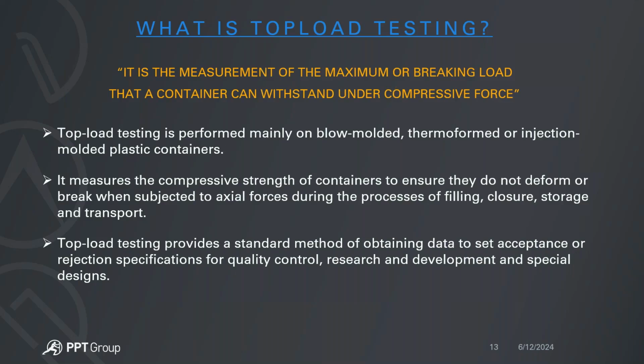One of the things that happens in any testing environment is once you've preset your pass or fail criteria for all future testing, you're then able to determine your pass or fail by saying, on this 20-ounce or 40-ounce bottle, we expect a minimum of 200 pounds. Anything above that is a pass. Anything below that is a fail. And that establishes testing standards for your testing environment in order to determine what's good and what's bad, and so on.